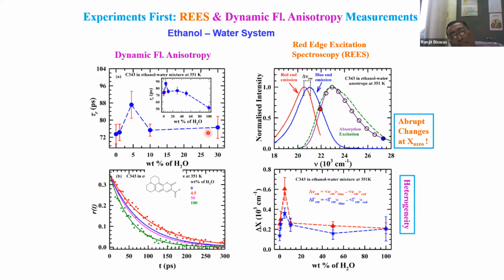If you add water drop by drop in ethanol, or alcohol drop by drop in water, the structure changes. First, the water tries to retain its three-dimensional structure by restricting its configurational entropy, and then finally it breaks down. It cannot host anymore. All those things are known for low alcohol mole fraction, and they are actually at the heart of the anomalous mole fraction dependence. However, we are now looking at the other end, the alcohol-rich solution. So it has to be the interplay between the hydrophobicity and the hydrogen bonding. There's that sweet spot composition, and it is different, right?